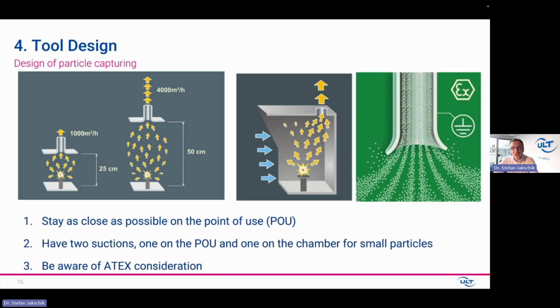And the second picture shows: also try to use a flow in the machine. Think about where the fresh air, the clean air, is coming from. This clean air should be above your battery cell, and you should capture the particles preferably behind the electrode material or the separator material, in order to avoid that any particle could settle on this material.